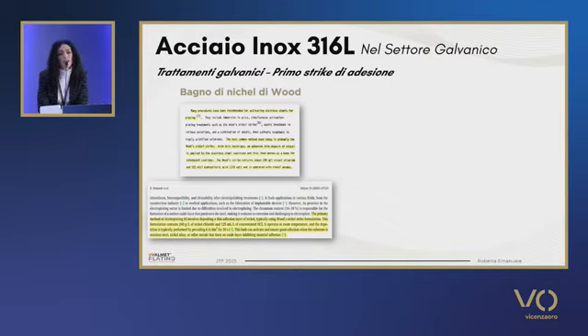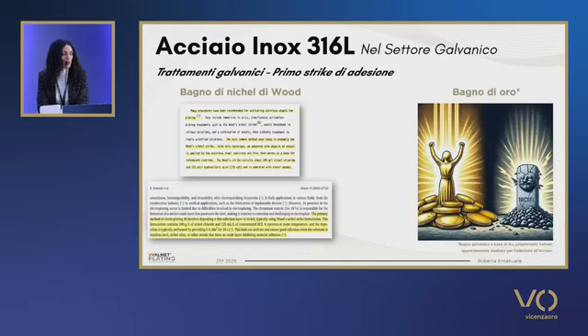We then looked at the role of the coating. As I said earlier on, the solution which is mostly used is the Wood's nickel bath, which is a galvanic bath with hydrochloric acid and nickel chloride. It is extensively used and has been since the 50s, and it is still being used even after the adoption of the legislation. In my work, we've looked at the nickel-free solution, which was gold-based, that has been studied to have the deposition of a metal on the external layer.